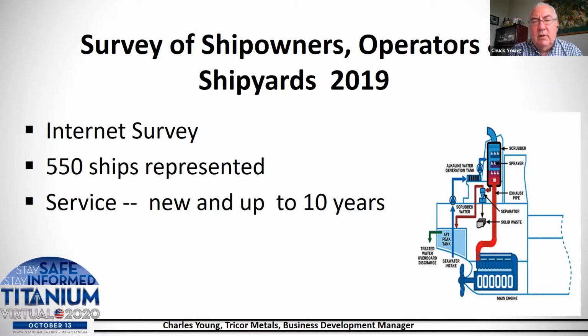Services for the scrubbers were fairly new, just installed, and up to 10 years of service. And if you look on the right side of this slide, you'll see where a scrubber is actually installed. It's installed right near the stack or in the stack. And most of the time that's right over the engine room. So if there's any problems with the scrubber, any leaks out of the scrubber system, it's probably going to go down to the engine room and cause major problems.